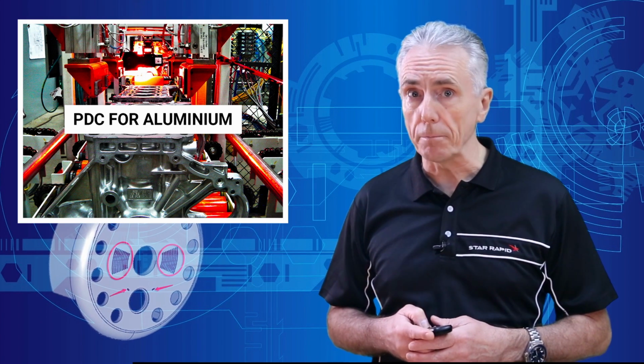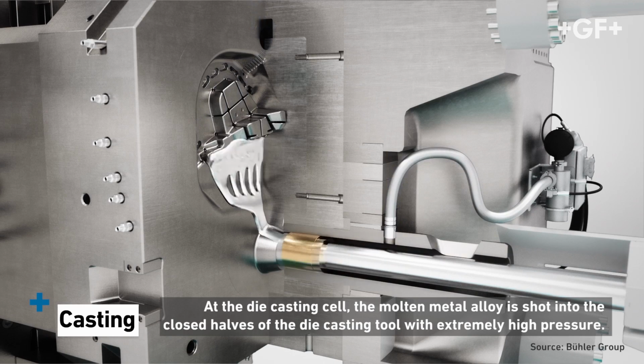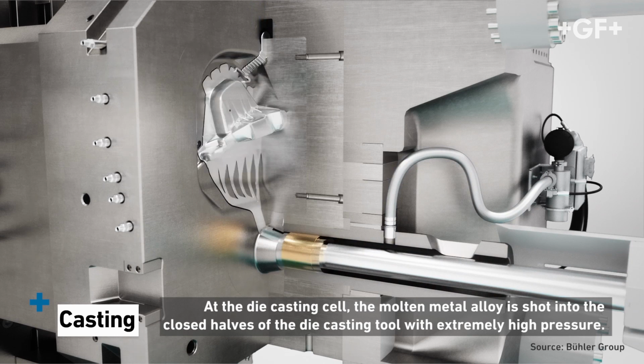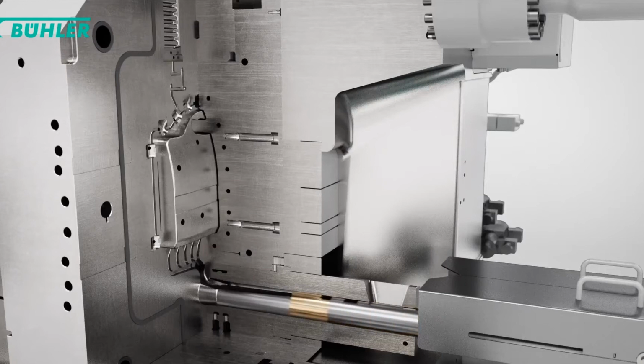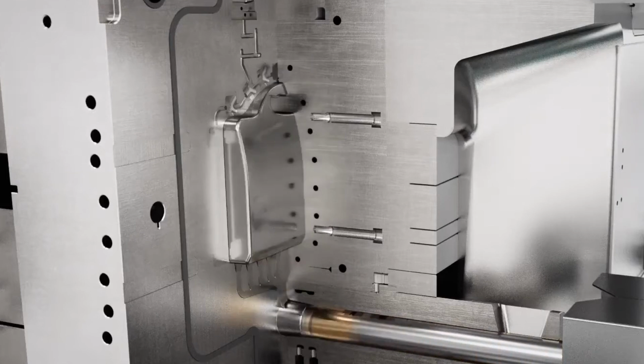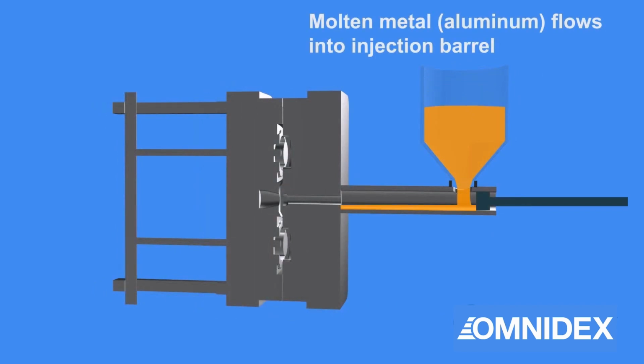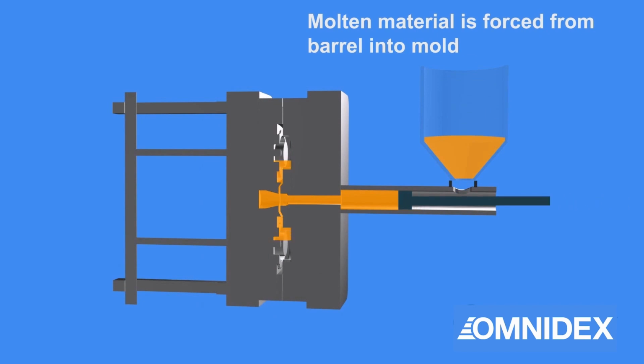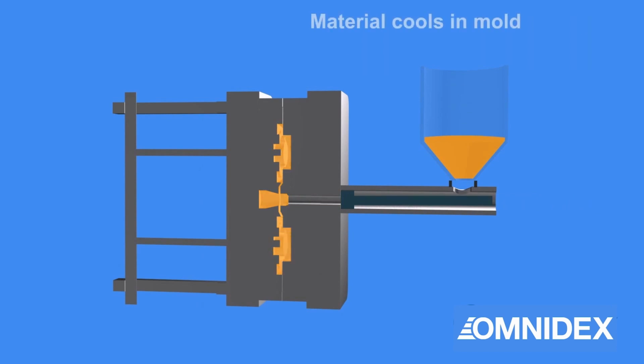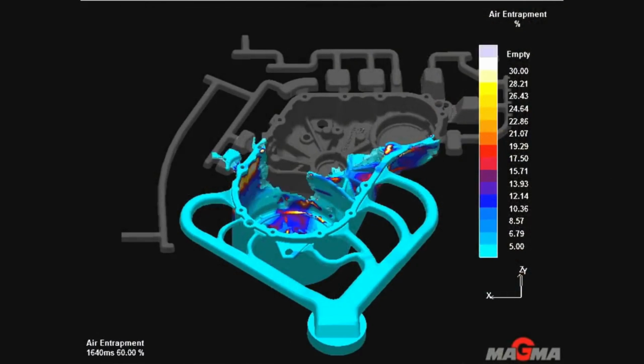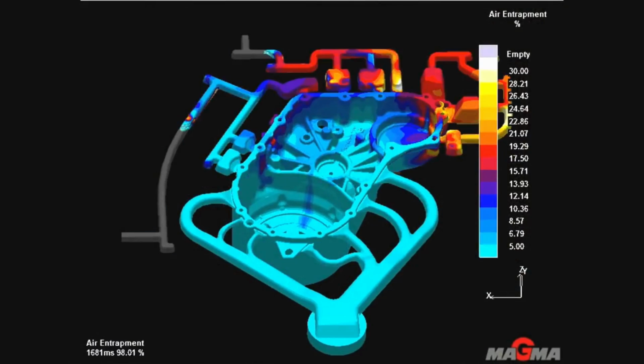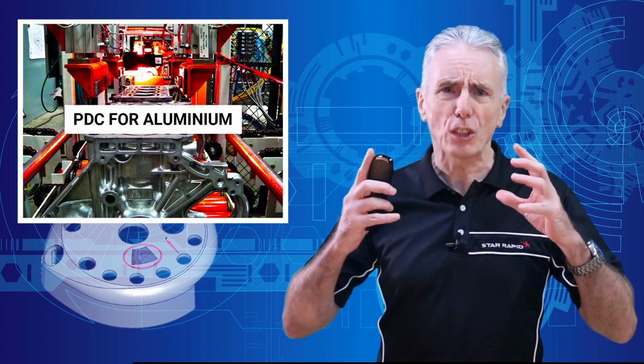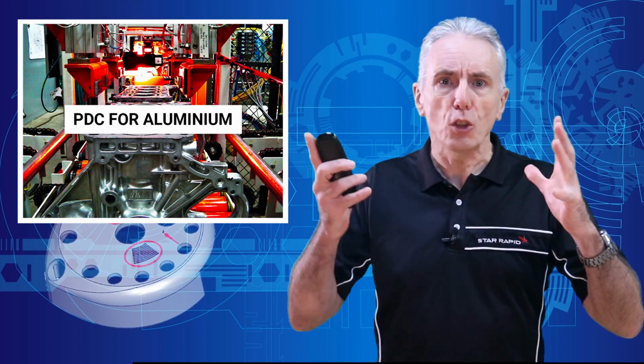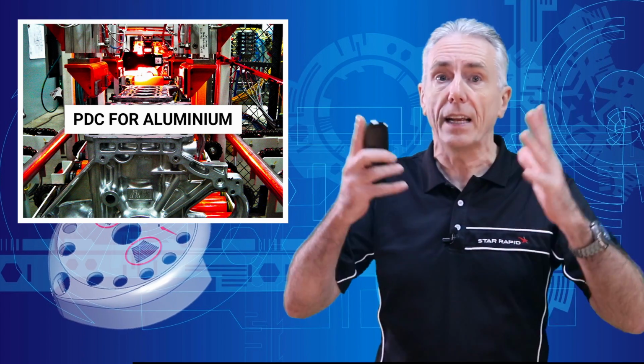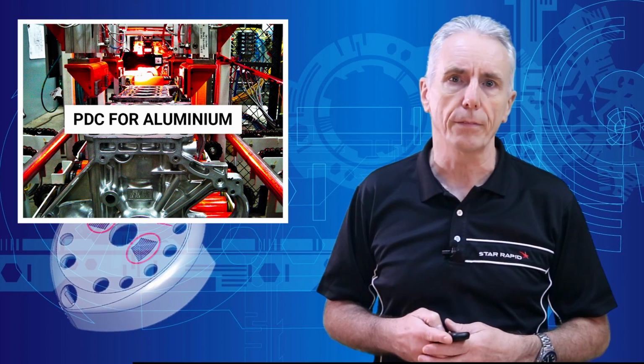Now for the really violent part. Stage 3, boom! The plunger pushes the entire shot into the cavity in a matter of just between 25 and 70 milliseconds, and for some much larger dies it can be up to a few hundred milliseconds. But this is fast, it's violent, and if the die has not been designed correctly, the air coming out of the vents can sometimes be so hot and moving so fast that you get supersonic screaming jets of fire, and that's why the vents are usually made of carbide.